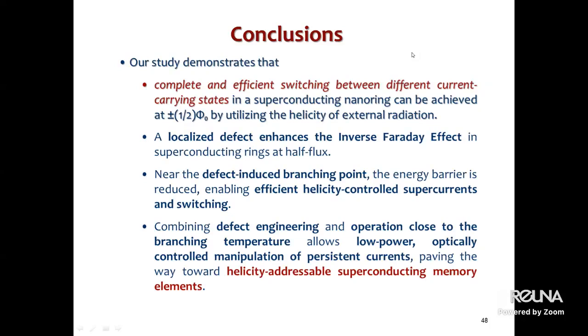Honestly speaking, I never worked with that, so it's difficult. Probably a second degree of freedom will appear. That means it will not be a quasi one-dimensional system. We'll have to take the second dimension into account in order to account for these magic angles, as I can imagine. So from this perspective, calculations will be much more difficult. But from the point of view of whether it's prohibitive or not, I would say not. So it's possible to calculate.